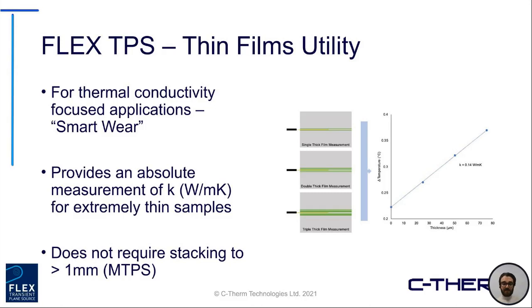And using the TPS thin films, it gives you a very simple, easy way to measure the thermal conductivity value of those samples, and you don't need to stack to that minimum testing thickness requirement that's outlined for the MTPS. So you can get away with a much thinner sample here, depending if this is an application that is of interest to you. Now, the thin films utility is obviously working off the TPS, or the transient plane source sensor. So it's a different method, and this would be something that would be available on the Trident platform. But just to highlight, it does offer some of those extended capabilities that may be valuable depending on the research and the products that you're working with.